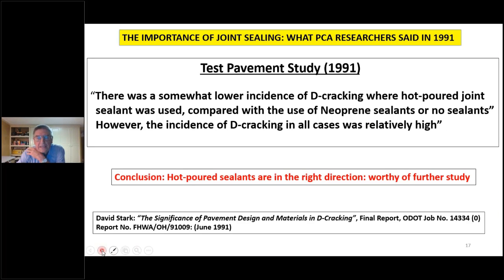PCA workers did look at that situation, and they are aware that there was a lower incidence of cracking where the hot pour sealant was used compared with the neoprene preforms. They said the incidence of cracking was still relatively high all over, but the conclusion there was that hot pour sealants are in the right direction, so they're certainly worthy of further study. And of course, these days we have a lot of synthetic polymers that weren't around back then that could function perhaps just as well.